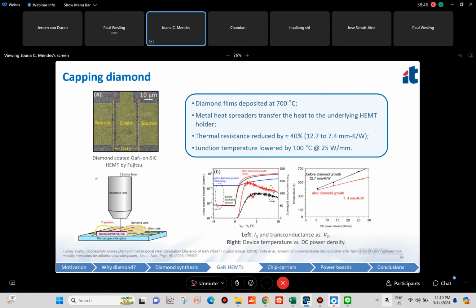They had to do a small trick though. They could not use the standard Schottky gate contacts because they were damaged during the deposition of diamond. So they had to use MIS structure as the gate contact.